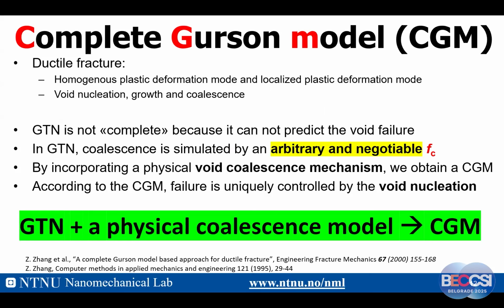That's a problem. Because of this weakness of the GTN, around 30 years ago I was inspired by Thomason's work. I tried to incorporate Thomason's model into the Gurson model. Because a complete ductile fracture model should include void nucleation, growth, and coalescence. GTN is not complete because it cannot predict the void failure. In GTN, coalescence is simulated by an arbitrary and negotiable FC. So by incorporating GTN with a physical coalescence model, we get the so-called complete Gurson model.